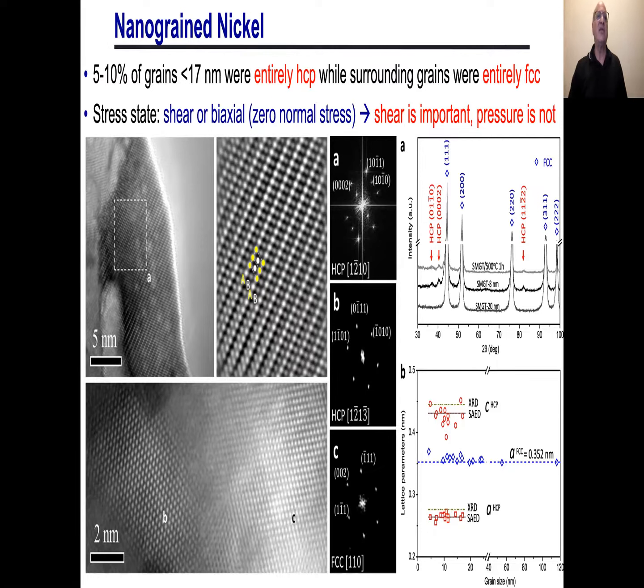And since this is close to the surface, there's no normal stress because of the zero traction boundary condition. And so that would suggest that the stresses there are shear or biaxial or something which is not hydrostatic. So this is a case where the hydrostatic stress is relatively small.